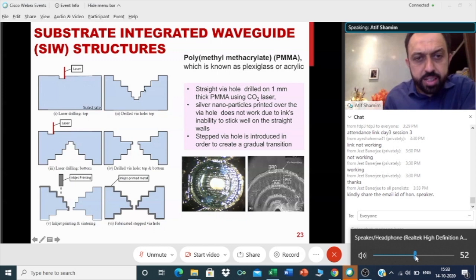So the solution we thought of was to make a staircase on either side, a staircase on the top and then a staircase on the bottom. Eventually we made them meet, and then we started printing. Now, because you have these horizontal surfaces where the ink can stick and very small vertical surfaces, we were able to print with a fewer number of layers, and there was no problem with the ink sticking to the wall. So that's how we connected.